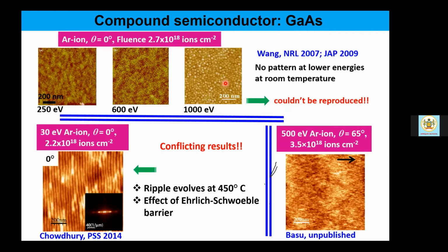At a much later study, using much lower energy, an order of magnitude less energy, in the tune of ultra low energetic argon ions of 30 electron volt only, at an incidence angle of theta equal to 0 degree and nearly comparable ion fluence, it was reported that beautiful ordered patterns are possible to be formed on the gallium arsenide surface for normally incident ion beams. And these ripples, ordered ripples, evolve at a temperature of 450 degrees centigrade during irradiation.